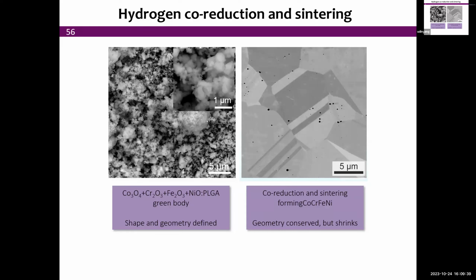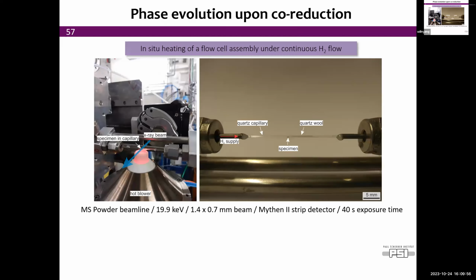And at the end, we have now a nicely fully sintered material. You see some twins here, you see grain boundaries. This is exactly the kind of structure you'd get if you were casting that very alloy, which is multi-principal element, as I said before.